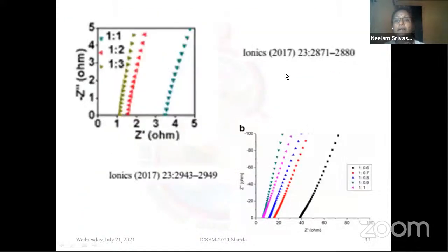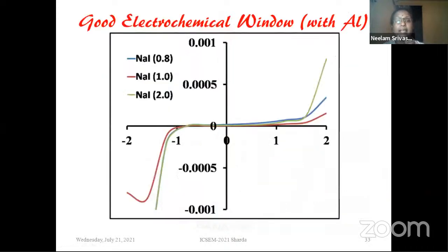So we have published many papers, and you can see the resistance is very small, less than 1. One thing I want to inform here is that this resistance is for a 0.8 thickness film, and the film thickness can be reduced many fold using simple techniques. So that indicates that you can have a very small resistance with these materials.